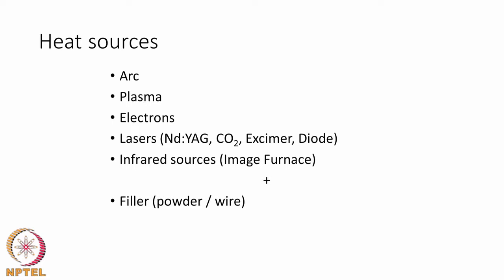We have not looked at infrared source as a welding source. However, we do have the possibility for surface treatment and surface coatings which form an allied process for welding. So, infrared sources also form one of the heat sources that we are looking at, and sometimes we have the filler which is being added. So, it can generate heat by exothermic reactions. It can also consume heat because it needs to heat up and melt and then mix with the liquid melt pool. So, you could also choose to have the filler wire or filler powder as a heat source or sink, but in our lesson we are not going to look at that. So, we are going to look at the top 5 items that I have listed here.